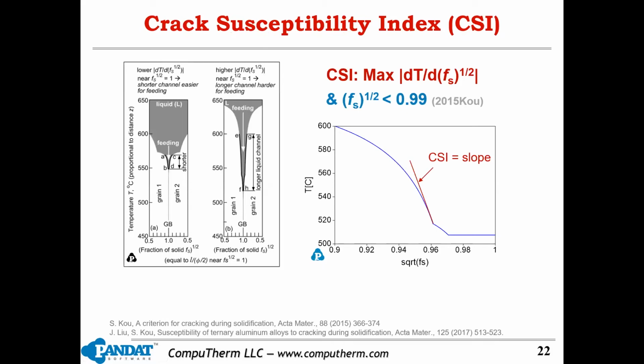In 2015, Professor Kou from University of Wisconsin-Madison proposed a criterion to evaluate the hot cracking susceptibility. In this criterion, the cracking susceptibility index, CSI, was defined as the maximum of dT over d square root of fs. T is the temperature and fs is the fraction of solid. So basically, if this CSI index is higher, that means you have a longer liquid channel to feed. Then it will easily lead to